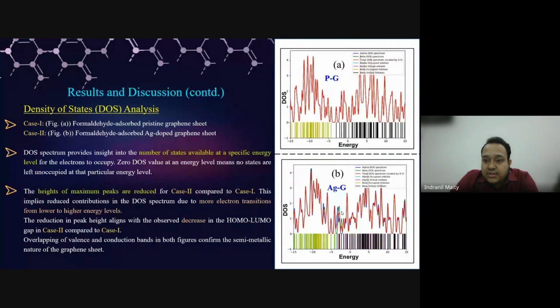And from the DOS, it can be observed that as the conduction band minimum and the valence band maximum are overlapping, they are semi-metallic in nature. Even in the case of graphene, we know that at the Dirac point, the conduction band minimum and the valence band maximum merge together, so this point also denotes the semi-metallic tendency.